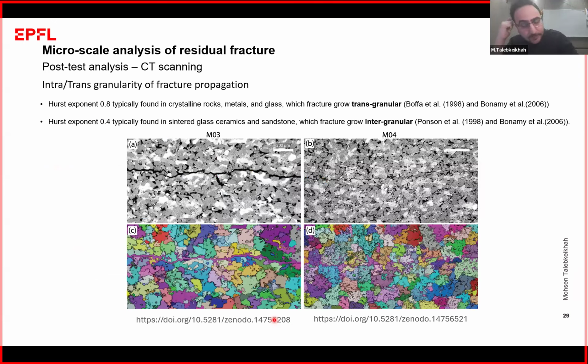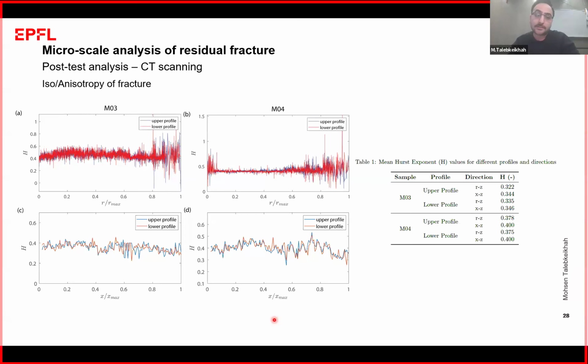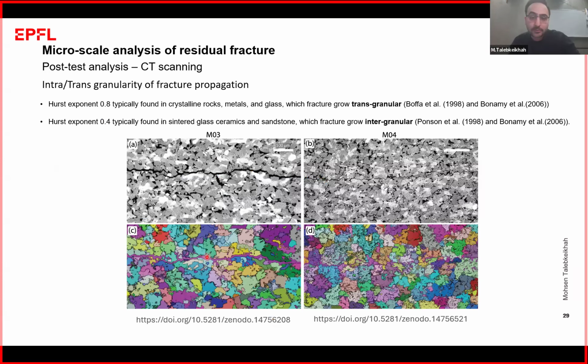And in the end, as we showed here, the Hurst exponent is a value close to 0.4. We saw in the literature that people mentioned that in sandstone samples, the fracture goes along the porosity and not through the particles, but surrounds the particles. They say this behavior happens when the Hurst exponent is close to 0.4. They also mentioned a universal value of 0.8, and showed that this behavior happened in crystalline rocks and materials, or glass or metals. They said that this 0.8 happens when the fracture propagates transgranularly.